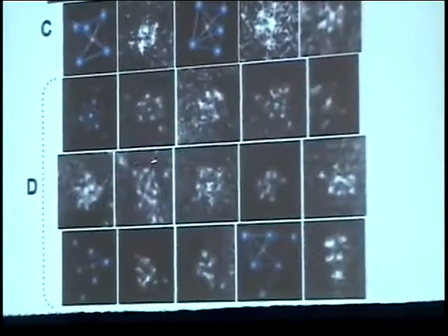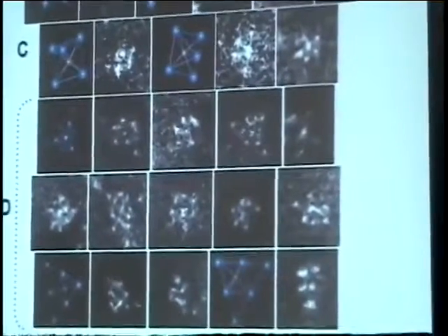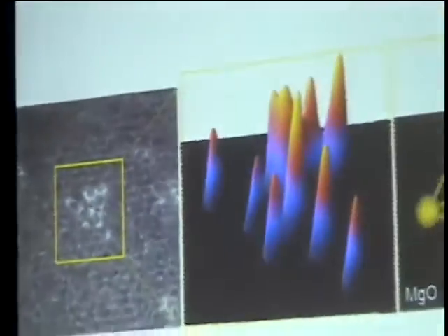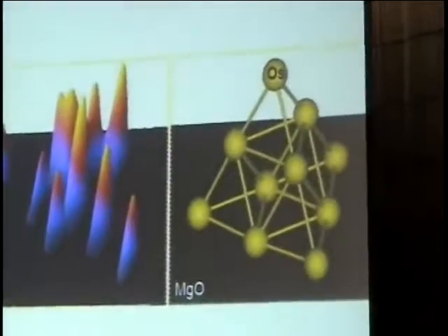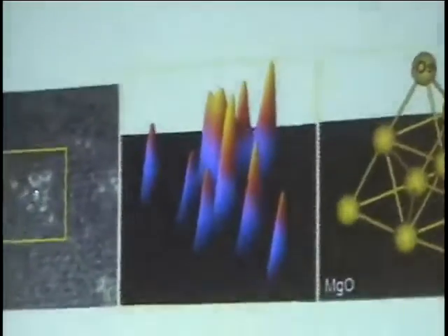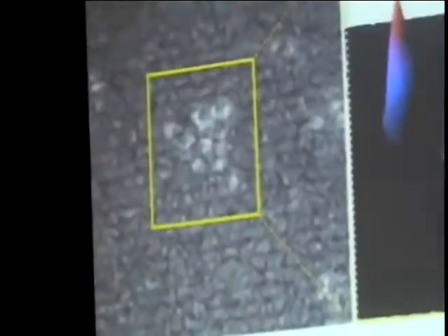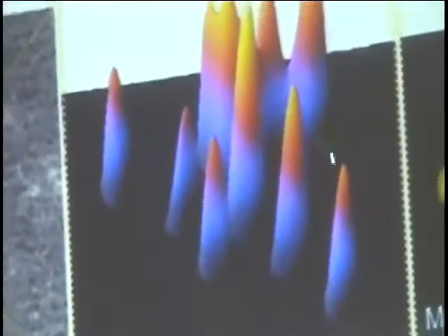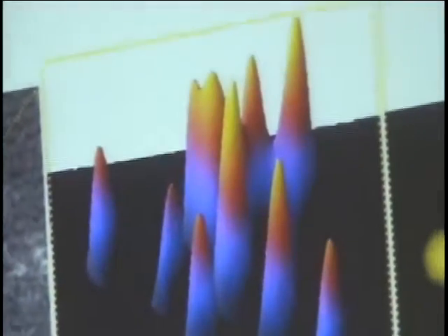And so you might be a little more skeptical of what I'm showing you. That's your privilege. So maybe a little more specific about how we're determining the number of metal atoms in each of these clusters. What we do is an intensity analysis, and I'm not going to give you detail about this, but my students spent months doing this. Take one particular image, like this one, which we call a deca-osmium, do the intensity analysis, and count them, 10 osmiums, indicating that it's really a deca-osmium cluster.